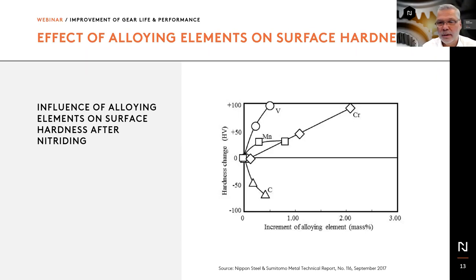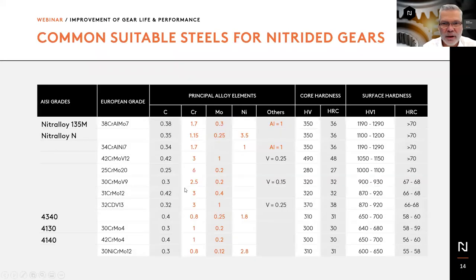This is one of the research conclusions where you can see that the addition of vanadium and chromium will increase the hardness of gears. Of course, manganese is there, but carbon will eventually decrease the range of hardness. However, it's to be taken up to a certain point, because in nitriding we are working with quenched and tempered materials, usually for gears. This means that the amount of carbon really defines the core hardness that you can obtain with the quench and temper process. So we can go to the next slide and perhaps look at a whole range of steels.